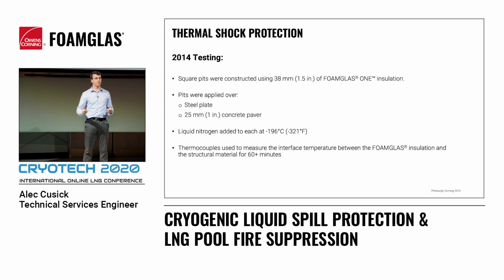This is a concept that foam glass has done many years of research on before we developed this exact system. Back in 2014, we conducted testing where we constructed square pits using 38 millimeters of our foam glass insulation. We then applied those square pits over a steel plate as well as a 25 millimeter concrete paver. Liquid nitrogen was added to each pit at -196 degrees Celsius. We then attached thermocouples between the foam glass insulation and the structural material and measured the interface temperature for 60+ minutes.